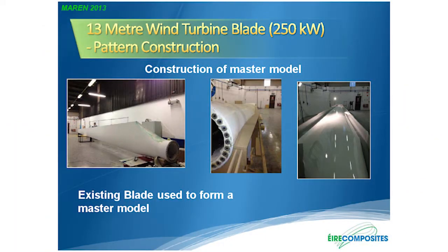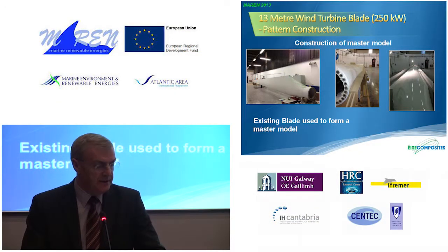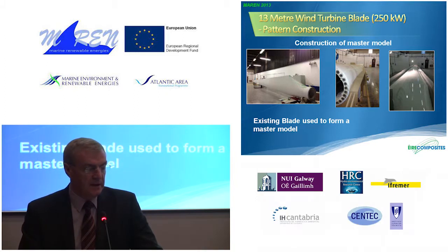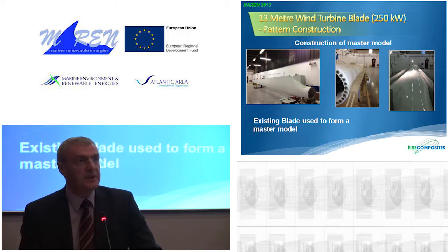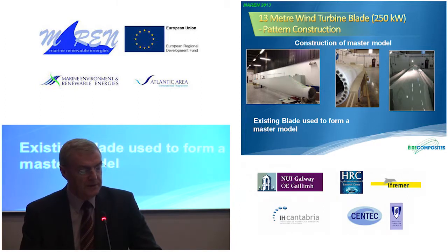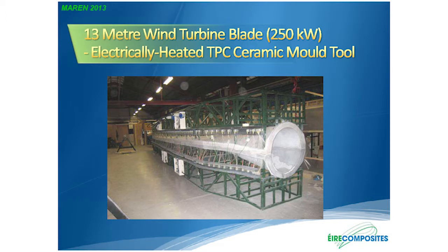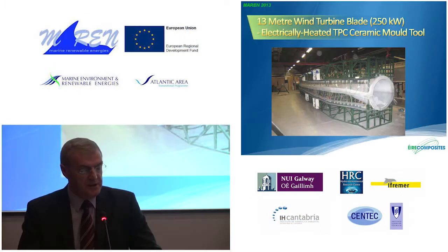We're now using this to build a 13-meter blade, and this is just some photographs of the steps we took to build the tool for that. An existing blade was used to form the master model, and then the ceramic materials that I described earlier were laid onto that to produce the mold. And this is a photograph of the mold. It's totally self-contained. There are no other ovens, etc. required. All that's required once you have that is to put the raw materials in, preform them, assemble the part inside, put your vacuum bags inside, close the mold and plug it in.